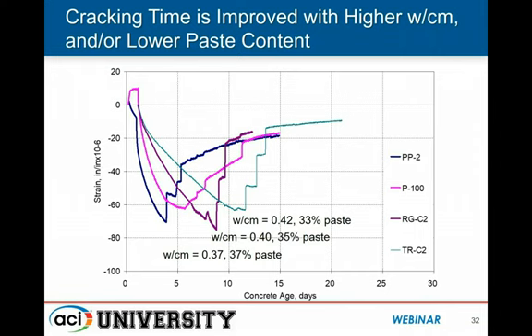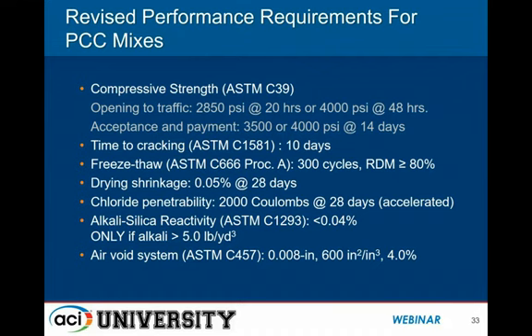This is a mixture that still gets 4,000 PSI at 24 hours. So it meets the requirements of the tollway patching system. And with a little healthy dose of accelerator, there were never any issues getting the strength in this mixture. So again, instead of relying on the cement to do this job, we're veering more towards accelerator dosage and trying to reduce the amount of cement that's in the system. And we're seeing great benefit from that.